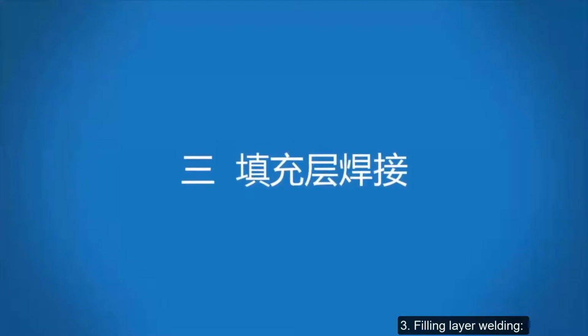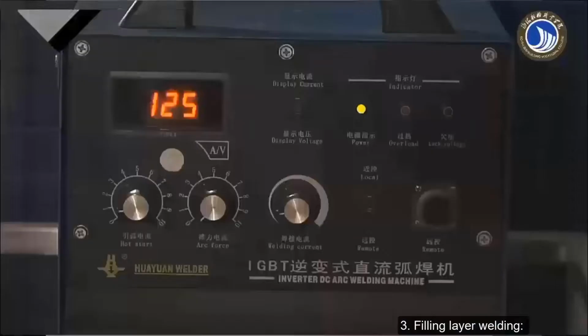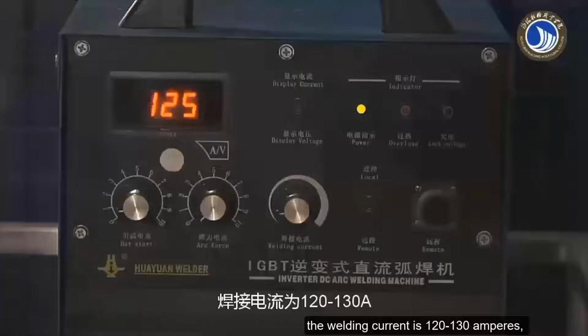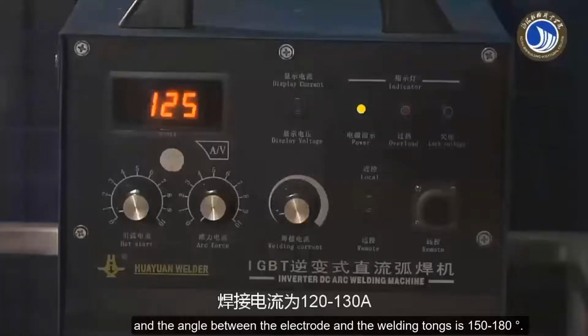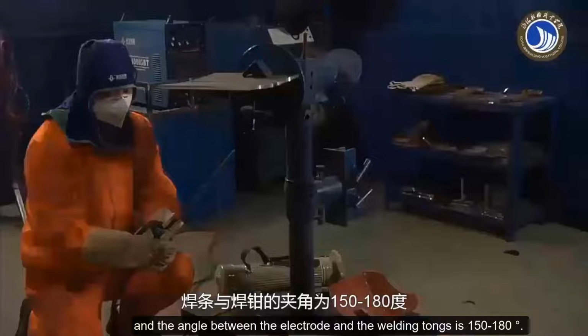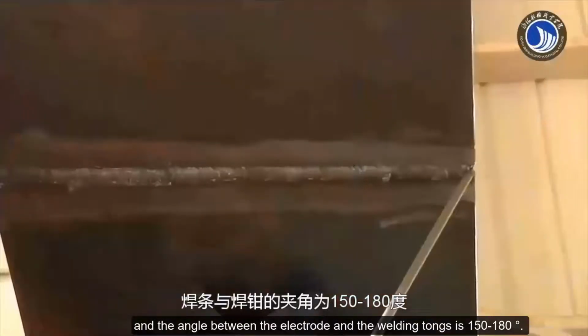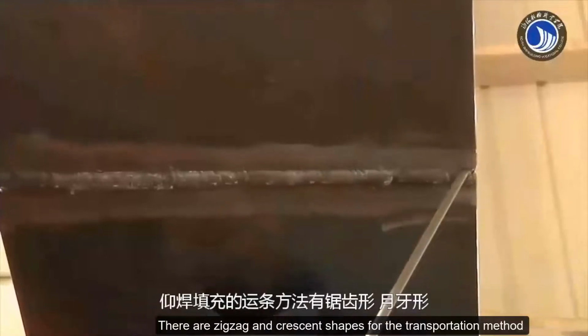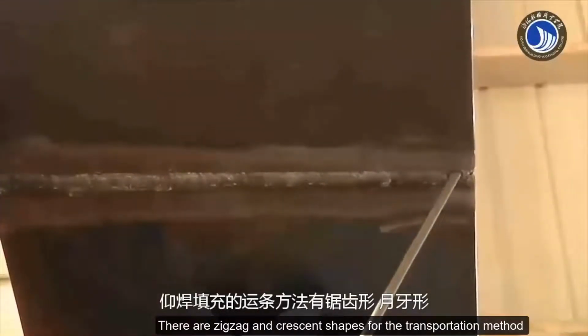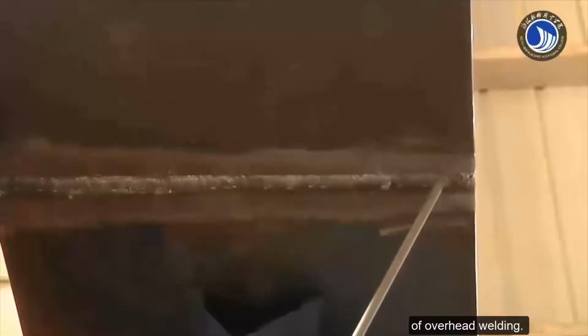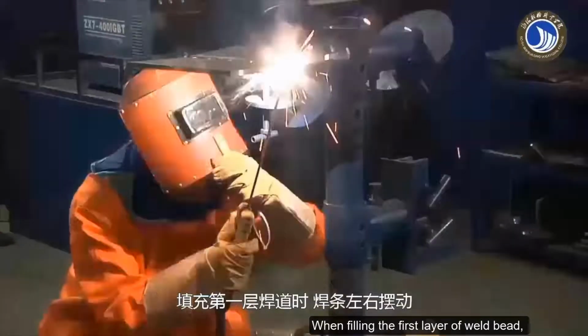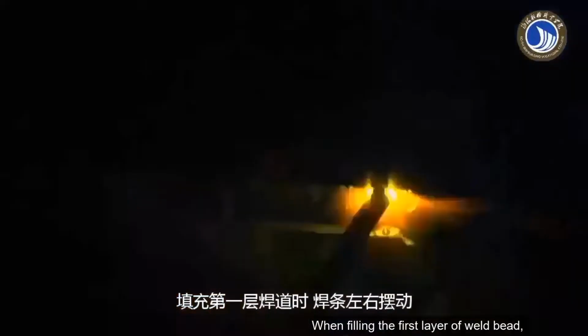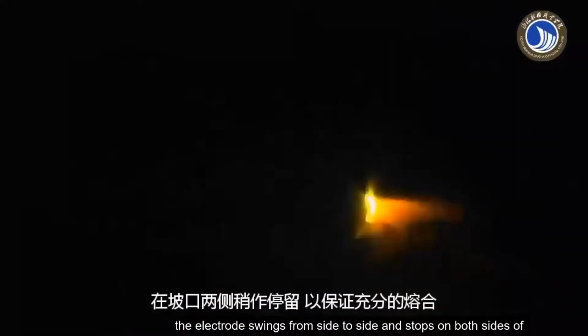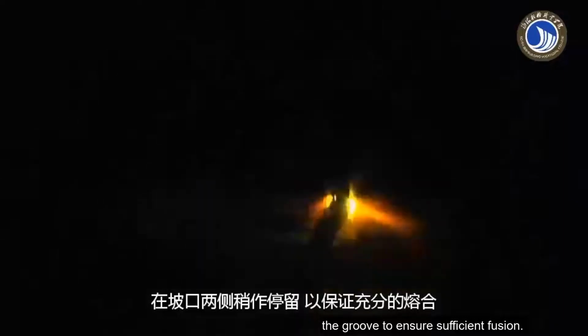3. Filling layer welding. The welding current is 120 to 130 amperes, and the angle between the electrode and the welding tongs is 150 to 180 degrees. The transportation methods for overhead welding are zigzag and crescent shapes. When filling the first layer of weld bead, the electrode swings from side to side and stops on both sides of the groove to ensure sufficient fusion.